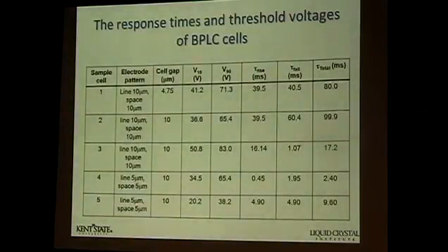But recently we are also using one of these additives to enhance this switching voltage. You can see that the switching on threshold voltage goes from 35 to 20, and from fully on at about 65 to 38. So it lowers that switching voltage, but you also sacrifice a little bit in terms of your response time, to roughly around 10 milliseconds. So on and off roughly around 5 milliseconds.